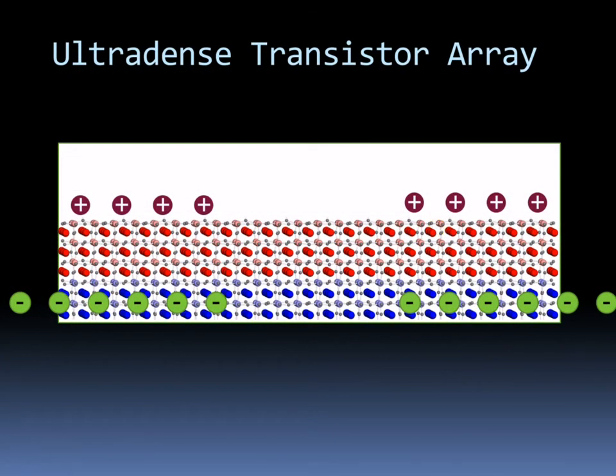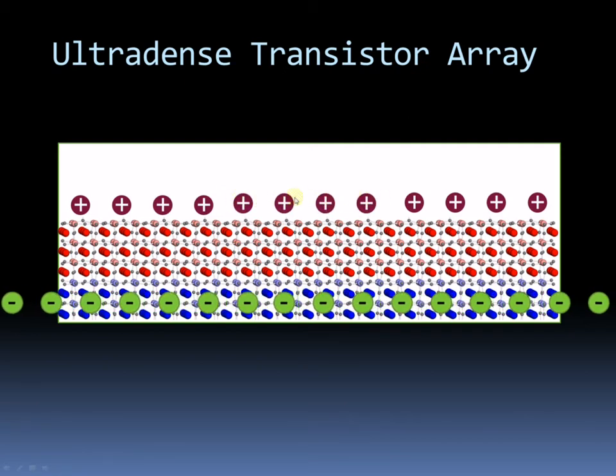The material that we're working with is very, very similar. You have a very thin layer here, 3-unit cells of an insulator, and in the absence of positive charges here, you might have 2 wires that are close together but still no conduction between them. And by writing on the top surface and depositing this positive charge, we're able to close this gap and switch the material to the on state. Now, in some sense, this is like an ultra-dense array of transistors. So we can string all of these transistors together in complex 2-dimensional designs to create a very broad range of device technologies, potential technologies.